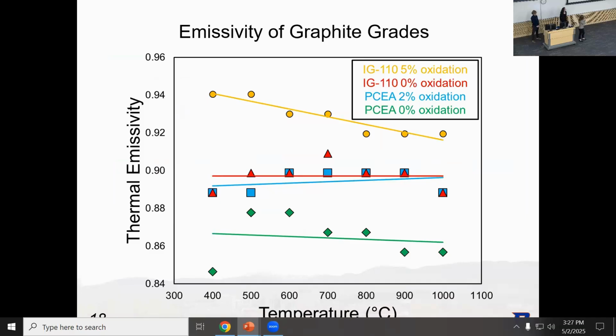I'll draw your eye to the yellow curve and the red curve, which represent the difference in emissivity between 5% mass loss and 0% mass loss IG-110. Our results align with our hypothesis that the oxidized graphite would have higher emissivity. Sort of as Lauren mentioned earlier, the logic there is that the mass loss will produce coarsening in the sample that will increase surface area for incident electromagnetic radiation, if not absorbed the first time, to sort of ping pong off of itself, off of all those little curvatures until it's finally absorbed and re-emitted, thus leading to higher emissivity.